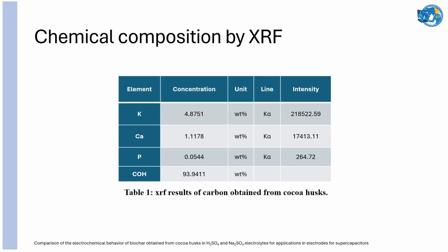As a result of chemical composition analysis by XRF, we obtained that a predominance of carbon is observed in the material, with the presence of 93% in weight. This is because cocoa pods are composed mainly of cellulose, hemicellulose, and various carbohydrates in the form of fiber in their structure. Additionally, elements such as potassium, calcium, and phosphorus were observed, which is commonly observed for this kind of soil.